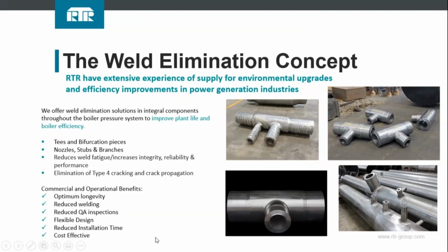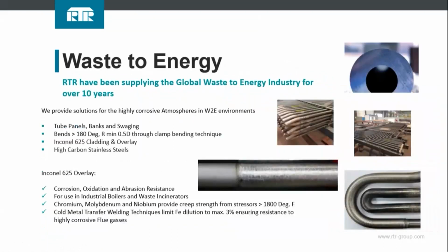And just to give an example, again, this double branched forging here, the T that we did, that was actually machined with a bend to allow for the fact that the boiler had sunk in its foundations on one half in service. So it really gives an indication of the level of flexibility that we have with these designs. And again, to reiterate, all of these parts, even 8-meter long spools like these, are completely seamless design, manufactured and forged from one piece of steel.